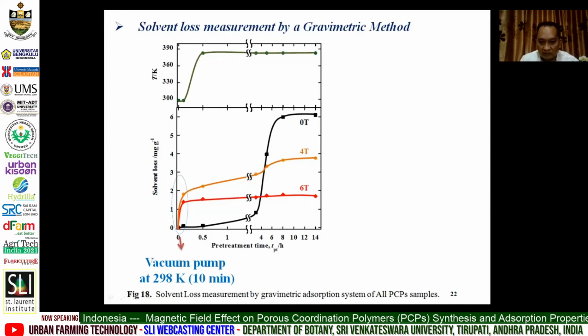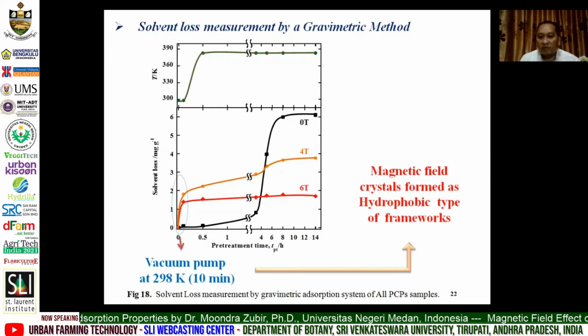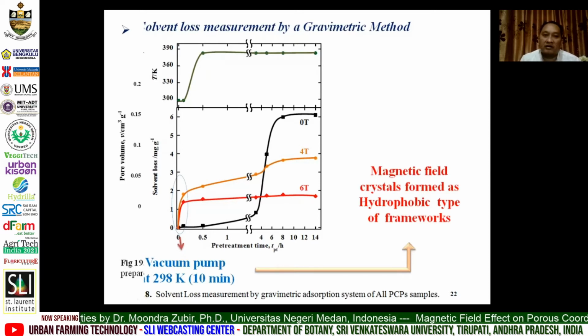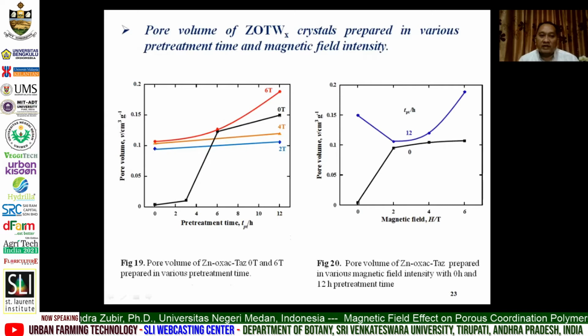The 0 Tesla, after 5 and 4 hours, the solvent gradually decreases or is removed from the crystal. So we consider that this magnetic field crystal forms as a hydrophobic type of framework. And to investigate the pore properties of this magnetic crystal and the without-magnetic-field crystal, pore volume was observed by various pretreatment time and various magnetic field.